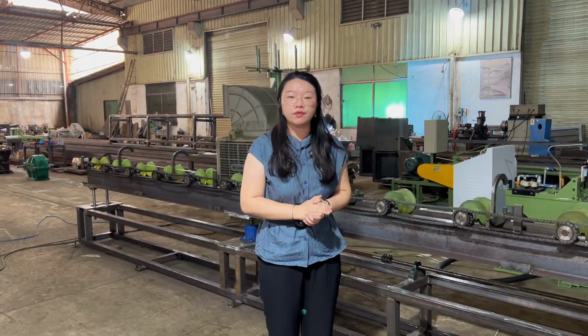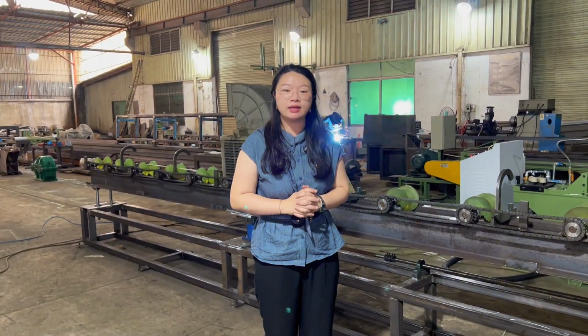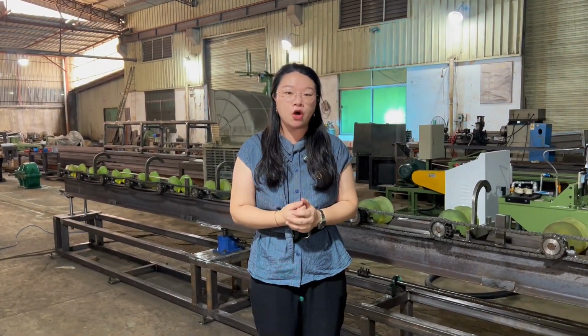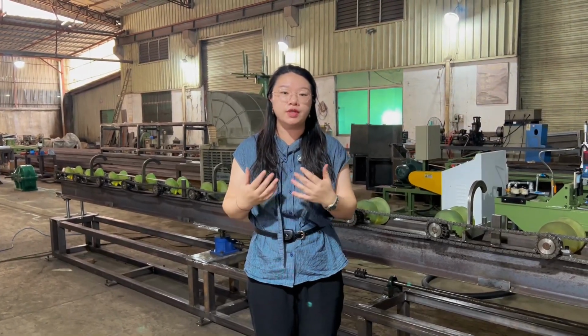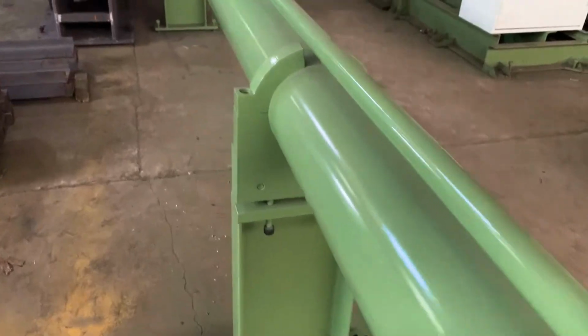Why specifically 10 tons of drawing force? The required force depends on the material yield strength, the reduction rate, and lubrication. For example, drawing a 25 mm OD mild steel tube down to 22 millimeters, a 12% reduction rate, needs roughly 4 to 5 tons. A 15 millimeter OD stainless steel tube with 15% reduction might need 8 to 9 tons. So a 10-ton machine gives you a safe margin for common precision applications without the cost and footprint of larger 30 or 50 ton drawing machines. It is the sweet spot for small workshops, research and development labs, and manufacturers of hydraulic cylinders, shock absorber tubes, or bearing races.